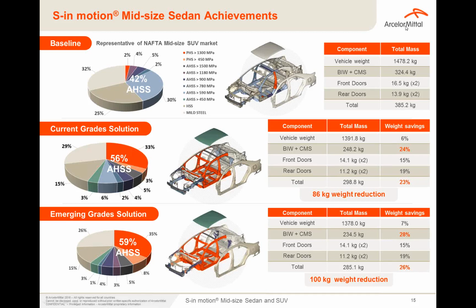And we also did the same exercise with emerging grades. And you see here we were able to increase this PHS amount up to 40%, with Usibor 2000, Usibor 1500 for some parts, of course, and Ductibor 1000, our new steel grade for hot stamping, which is very efficient in energy absorption. So we found very new applications for that grade, which are very, very efficient for lightweighting. And you see that we achieved 100 kilogram weight reduction for that solution with emerging grades, leading to a very low body-in-white, as you can see on the table, at 234.5 kilogram. Sorry.